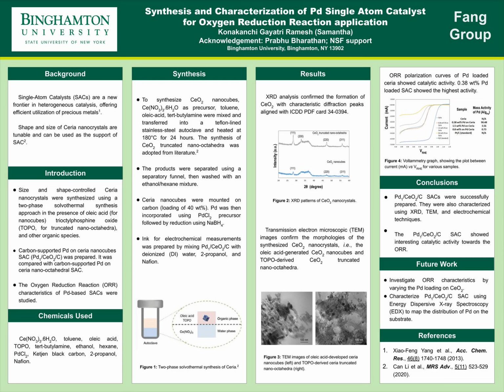Moving on to the conclusions and future work. From my study, we can conclude that palladium single atom catalysts can be synthesized using different morphologies of CeO2 support. The catalyst with 0.38% by weight palladium loading exhibited the highest catalytic activity for ORR reactions for fuel cells.